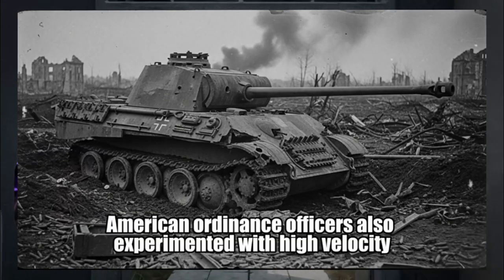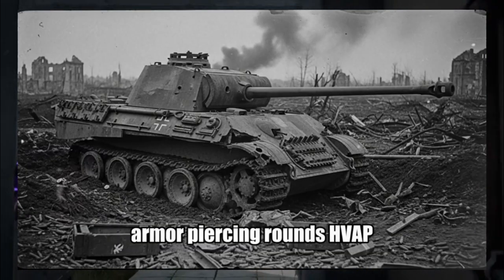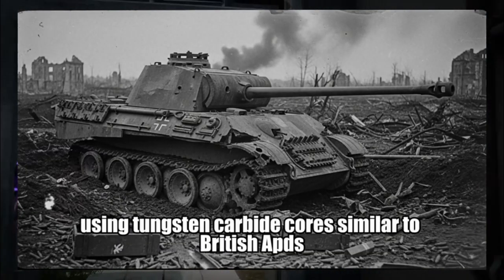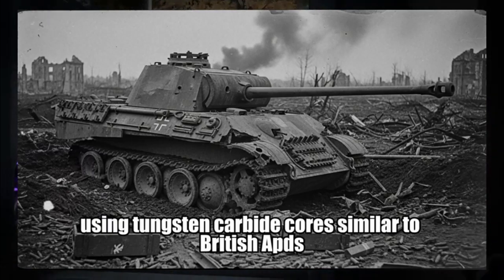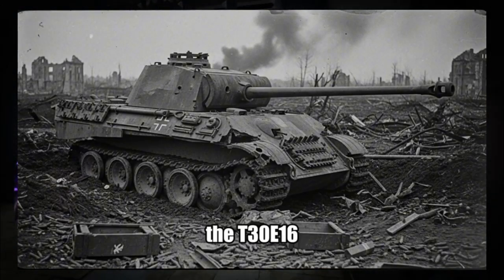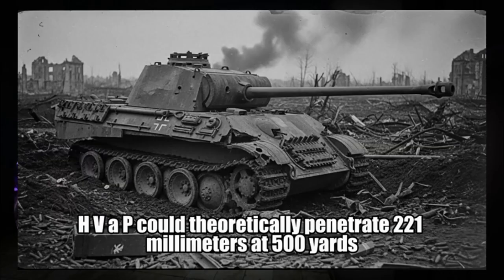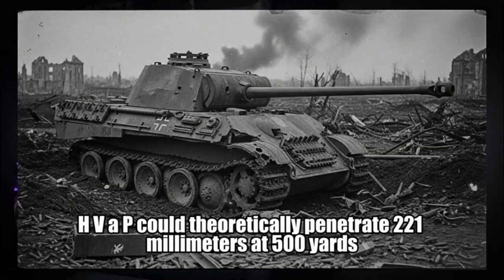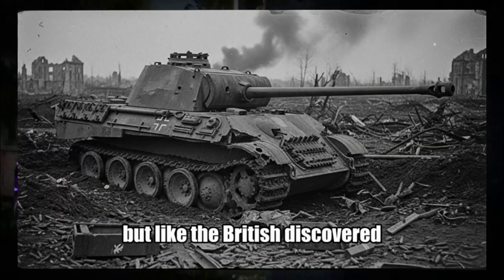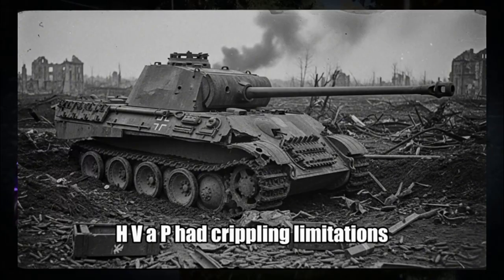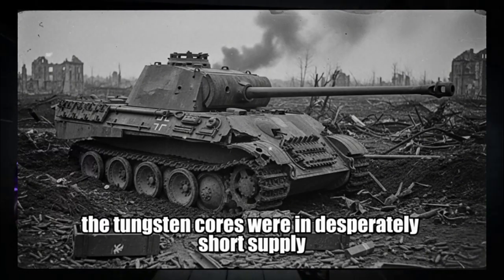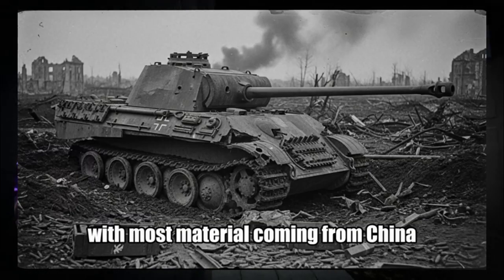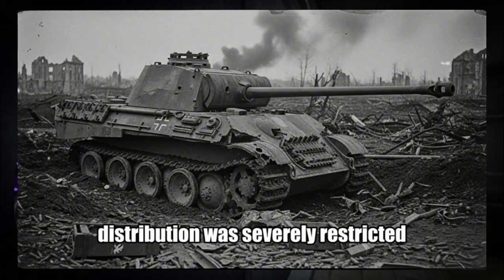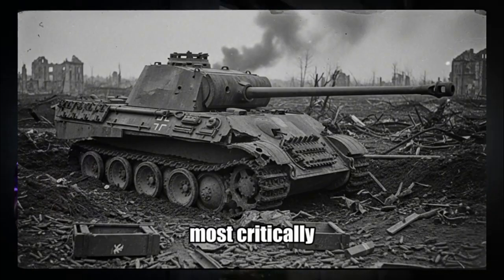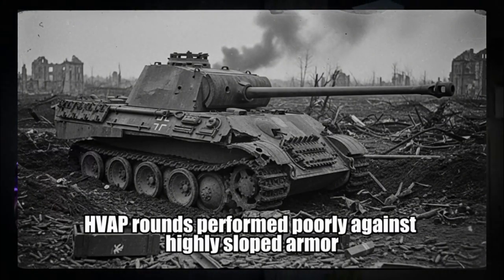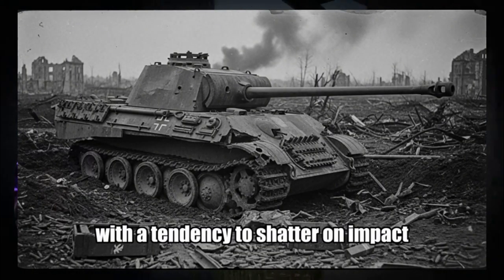American ordnance officers also experimented with high-velocity armor-piercing rounds, HVAP, using tungsten carbide cores similar to British APDS. The T-30E16 HVAP could theoretically penetrate 221mm at 500 yards. But, like the British discovered, HVAP had crippling limitations. The tungsten cores were in desperately short supply, with most material coming from China. Distribution was severely restricted. Most critically, HVAP rounds performed poorly against highly sloped armor, with a tendency to shatter on impact.